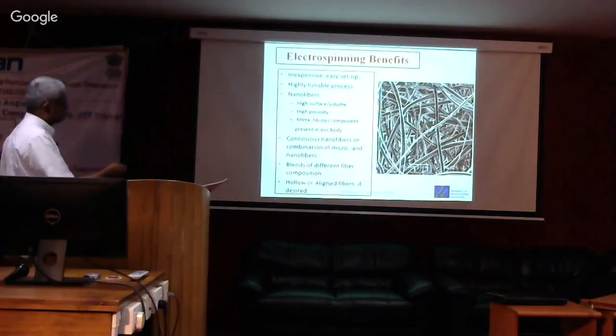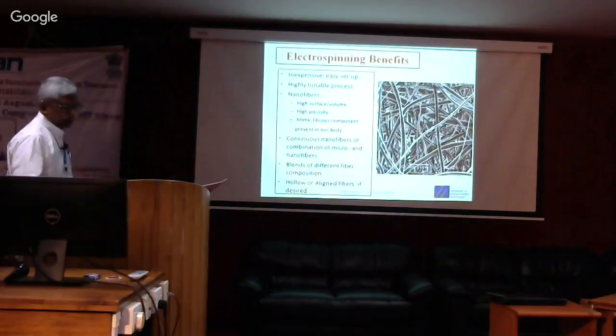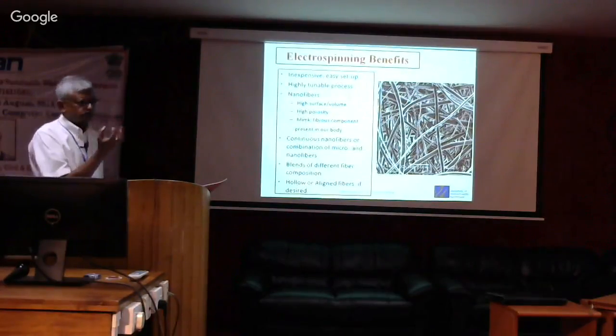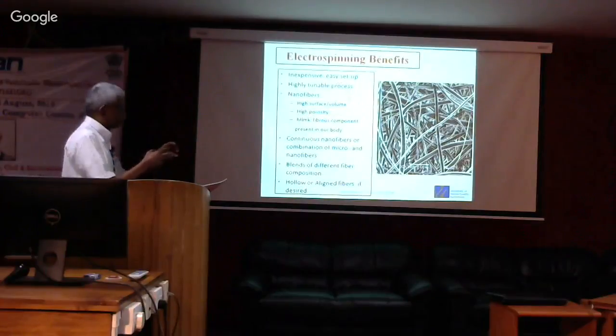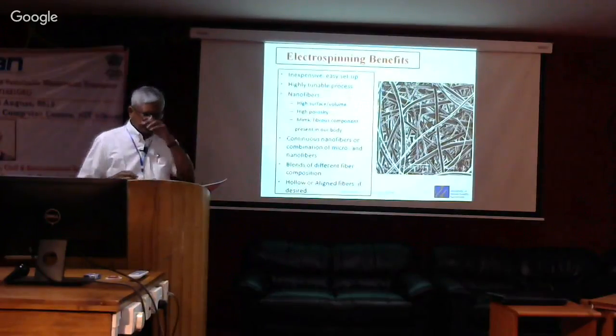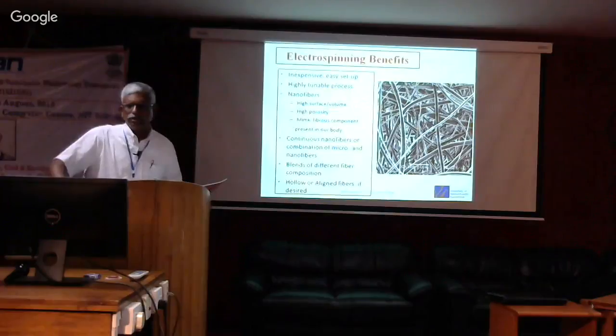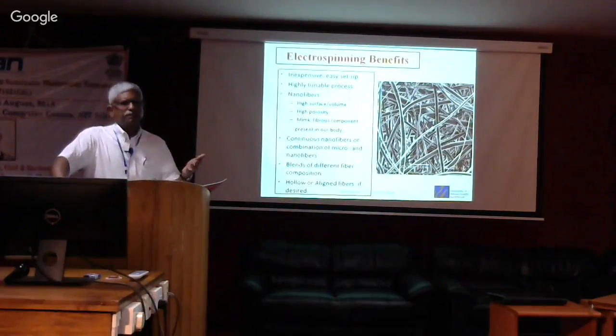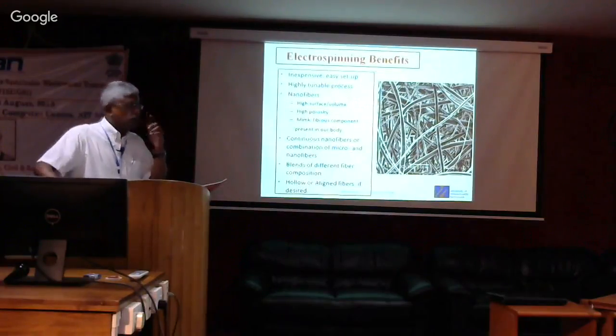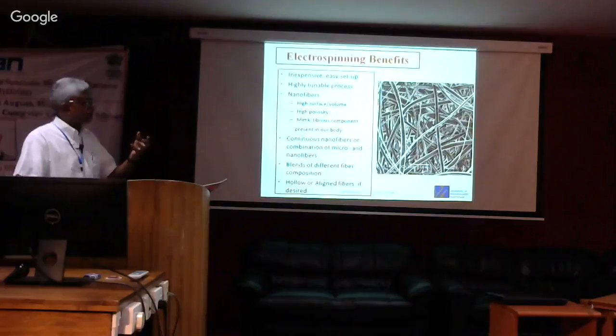They do have these benefits, very tunable, because we have full control of the starting polymer. We have full control over the solvent, and we have full control over the distribution. Typically, the data that I will show you is about, let's say, 5% polymer, 95% solvent, 6% polymer, 94% solvent. So you can change this mixture.